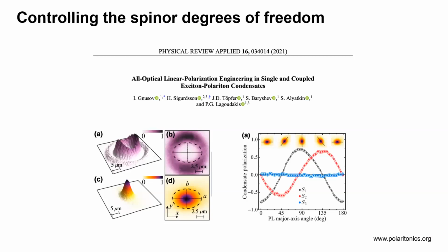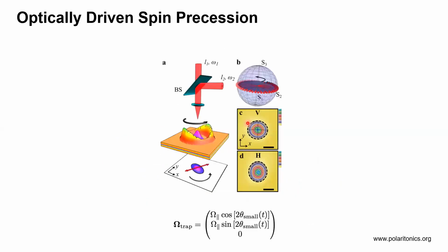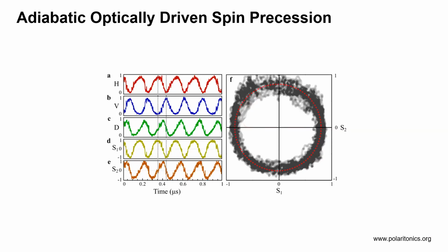I put now my composite beams, and I have a pseudo-spin, if you like, of 1/2, which is on the XY plane of the Poincaré or the Bloch sphere, as you like. And now I can rotate this with gigahertz. So let me do it. And what we see is the following. If I rotate slowly, microseconds, 0.2 microsecond rotation, I see that the 3 degrees of freedom here, so horizontal, vertical, diagonal, it rotates on the XY plane of the Poincaré sphere. So I have a linear polarization that rotates slowly and it follows the rotation of this elliptical trap. Okay, so it follows the rotation.